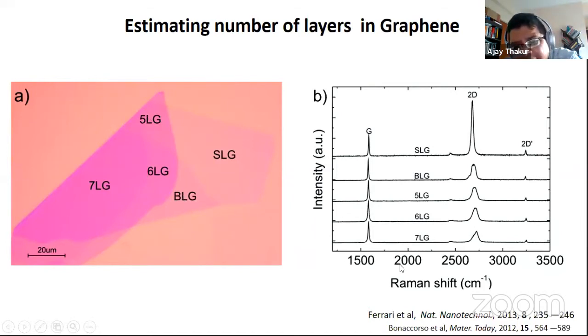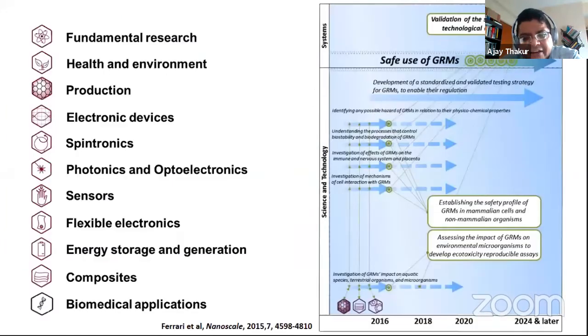And very soon people developed technologies to figure out the classification of single layer to multi-layer graphene via looking at the full width half maximum of the corresponding 2D peak in Raman spectroscopy. So therefore, graphene turned out to be a real material with a lot of interesting applications.